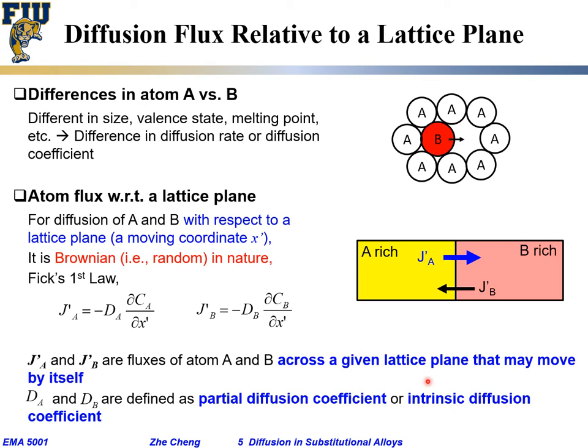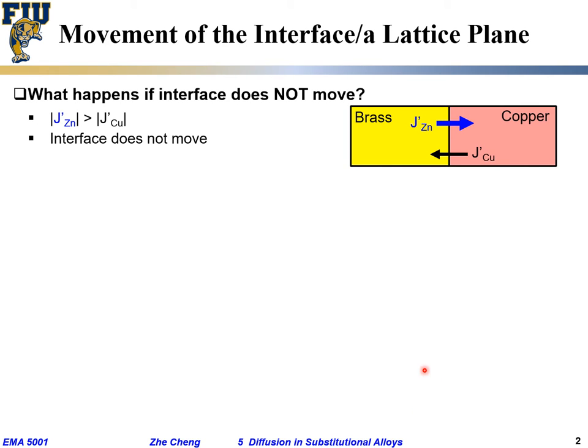I put intrinsic here, which means that's totally due to the thermal vibration, random Brownian motion. You're sitting on that bus, random motion on both sides. Okay? Now let's say we have brass on one side, copper on the other side. Zinc goes one way, copper goes the other way. And we said, okay, let's assume with respect to my moving interface, J zinc is greater than J copper.